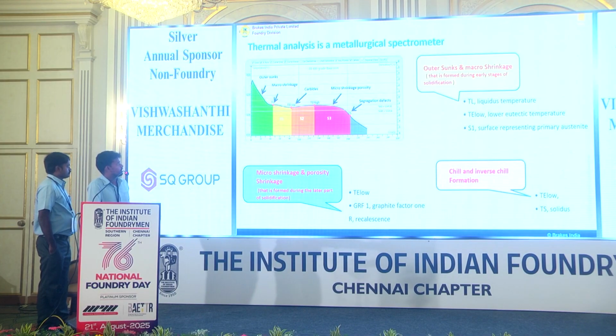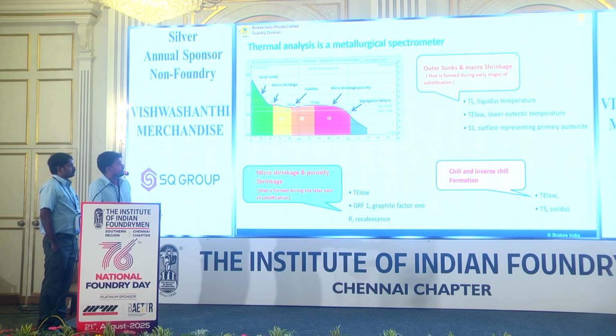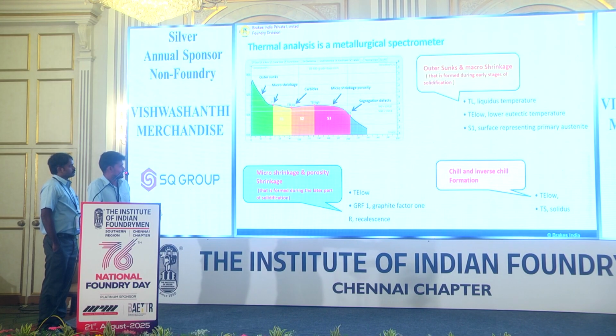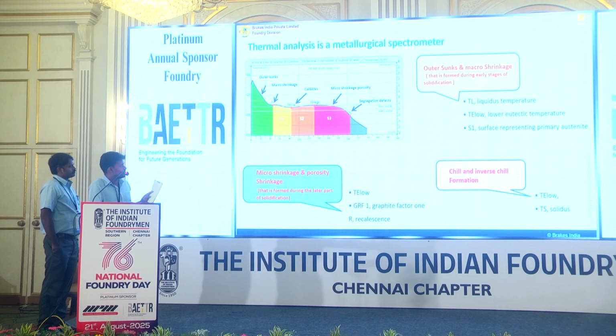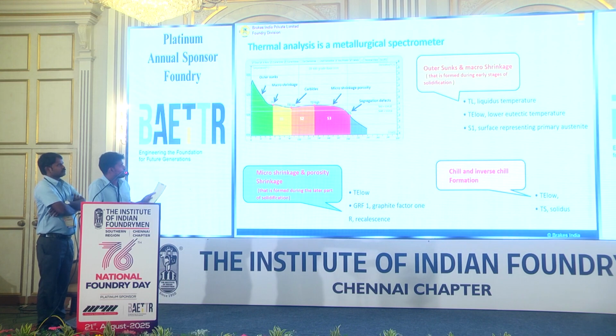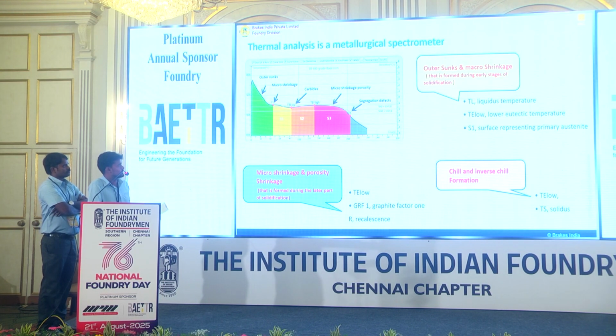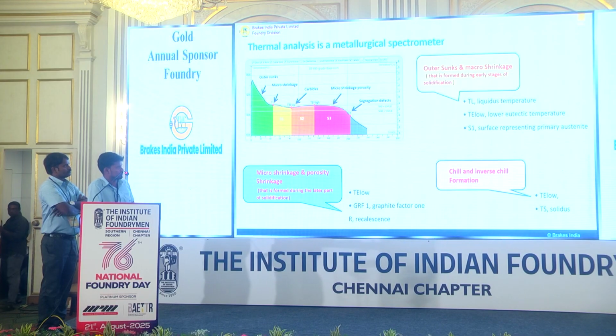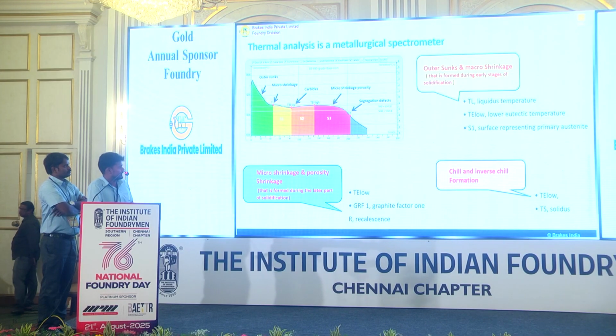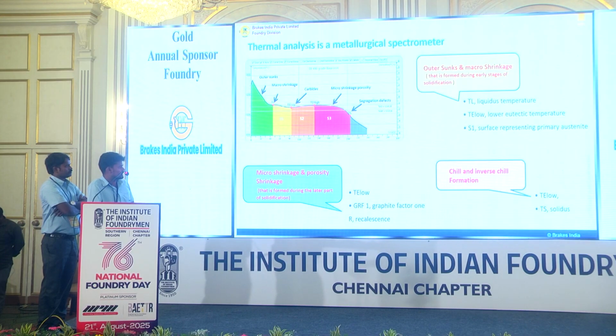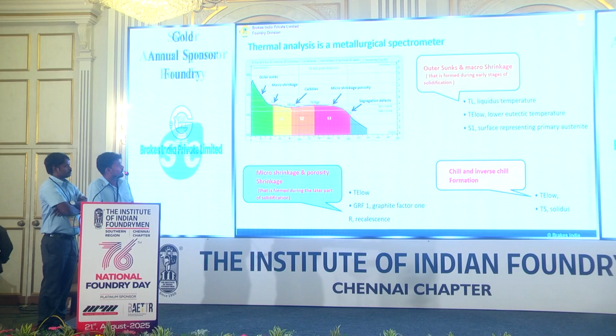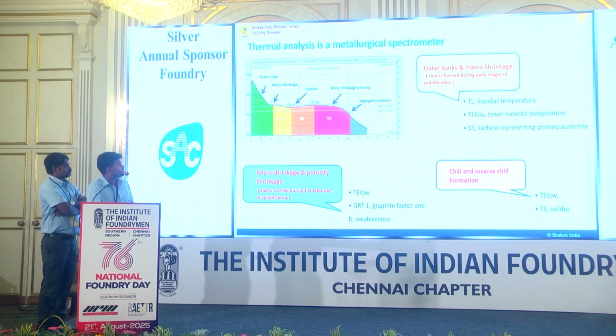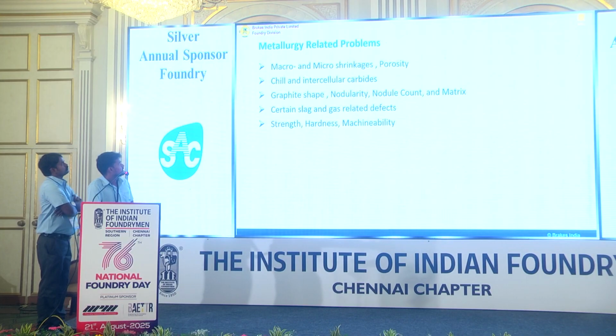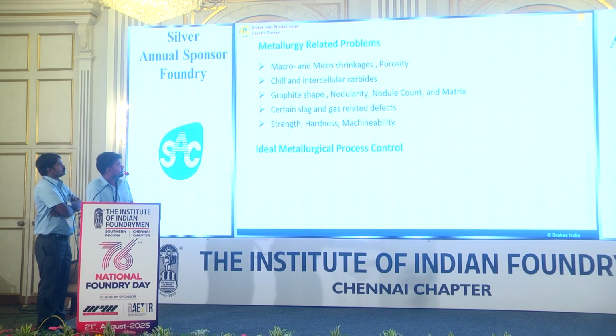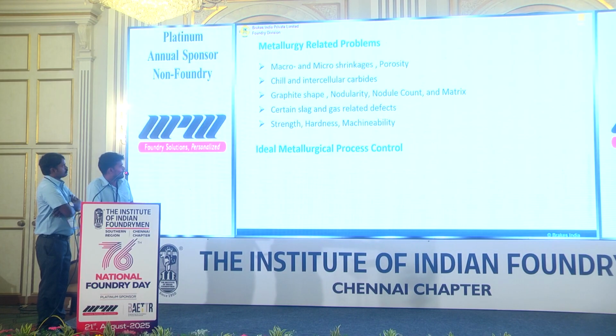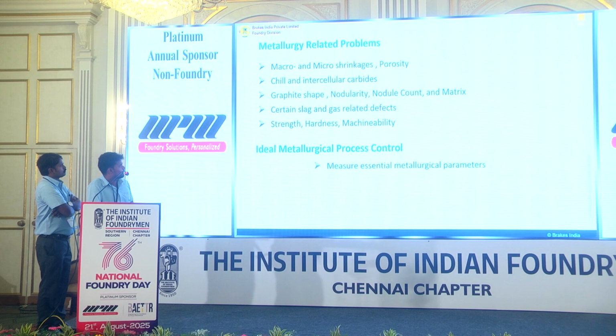Thermal analysis is a metallurgical spectrometer. It gives information on macro sinkages, micro sinkages, porosity, and inverse chill. These defects can be controlled through thermal analysis parameters like TL, the liquidus temperature, TE low, the eutectic low temperature, S1, the surface representing primary austenite, graphite factors, and recalescence. Those are the key parameters for controlling those defects. Some metallurgy-related problems can be solved through the above parameters I mentioned.